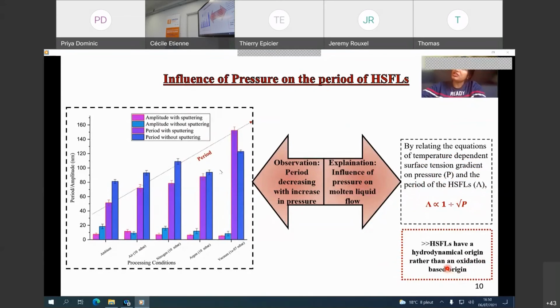So we began with an investigation to study the influence of oxidation on the formation of HSFLs, and we found out that oxidation or other gaseous environment has a very negligible role in the formation of HSFLs, and ultimately we concluded from this observation that HSFLs have a hydrodynamical origin, or they are most likely to be explained by molten liquid flow rather than oxidation-based modes.